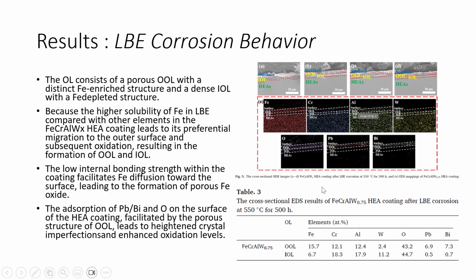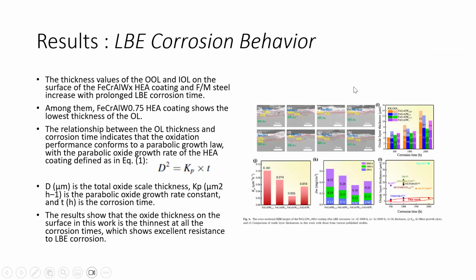We can see in this figure the concentration from the outer oxide layer and inner oxide layer. The adsorption of Pb, Bi, and oxygen on the surface of the exterior coating is facilitated by the porous structure, which has high-density crystal imperfections in the oxidation layer. The thickness values of the oxide layer on the surface of the samples still increase with prolonged LBE corrosion time.